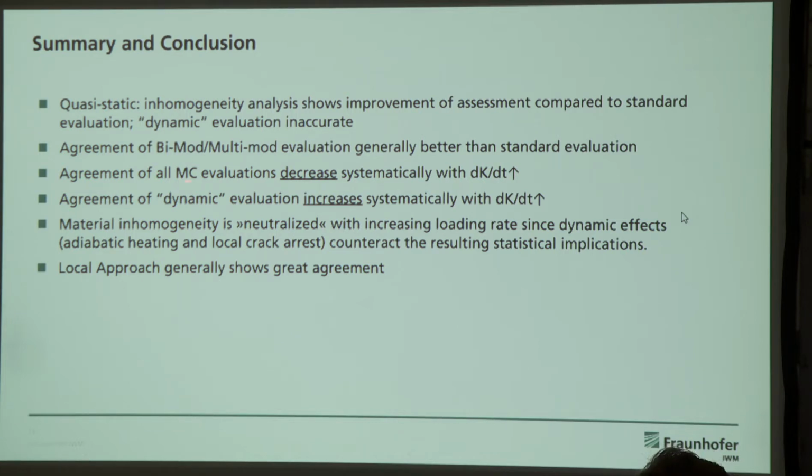But generally, you could also see that the agreement of these master curve evaluations decreases systematically with an increase of loading rate, and contrary, you see that the appropriateness of the dynamic master curve evaluation increases systematically.